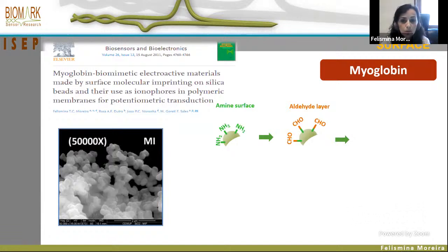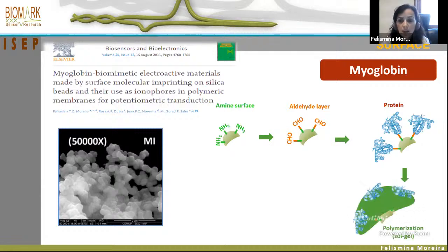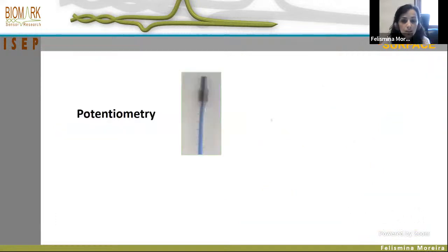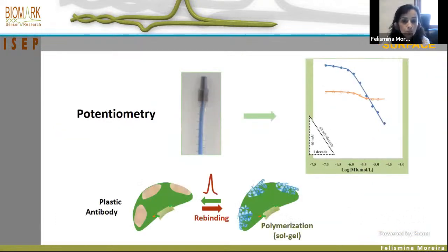Next, we introduced aldehyde groups by modification with glutaraldehyde, in order for the protein to attach covalently on the bead surface by establishing an imine group. Then the polymerization was carried out by sol gel. And the last step consists in the template removal from the polymeric matrix by acetic acid treatment.